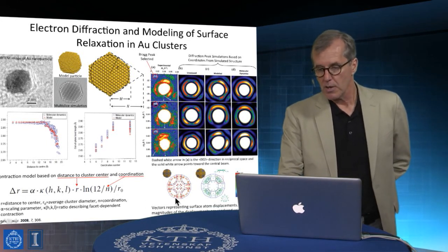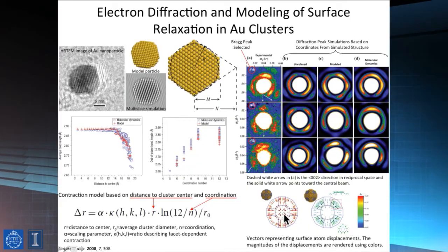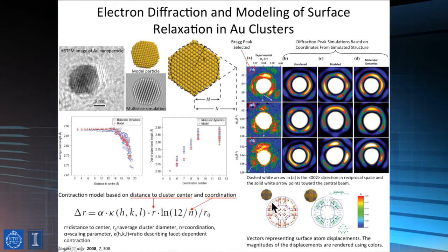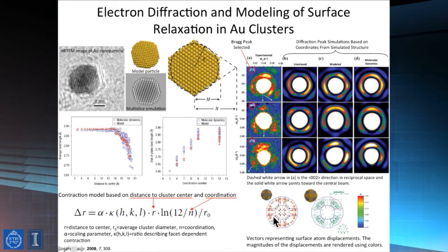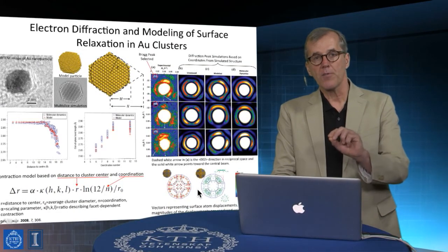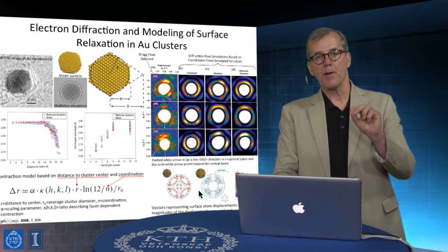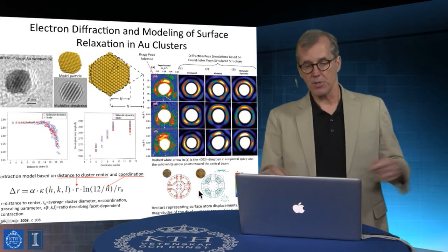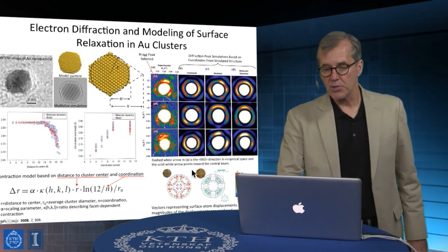So, we have atoms that are present on terraces, and they might be 111, 100, etc. And we have edge planes, we have vertices, and basically the atoms that are present in all these different places relax from idealized atomic positions. And actually this data allows you to determine that.